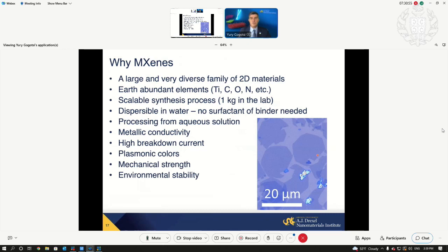But all this is only important if these materials bring properties other materials don't have. And they do. They are the most conductive, truly metallic two-dimensional materials, about an order of magnitude more conductive than, say, reduced graphene oxide, the typical type of graphene used in manufacturing composites, films, and so on. They also have very high breakdown current, 2 orders of magnitude higher than copper. So you can lodge a high current through even a large single flake, single monolayer, nanometer thin flake of MXenes.